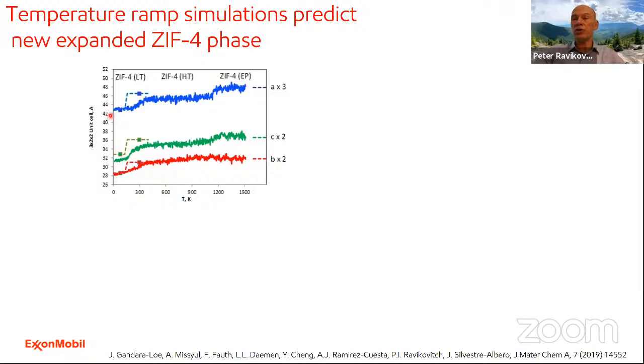When we did these simulations using the snapshot method with the temperature ramp on ZIF-4, we started with the low temperature structure. Then there is a transition to the so-called high temperature structure, and this is in agreement with experiments. Experiments are the dashed lines. But then upon further heating of the material to unphysically high temperatures, which we can do in computer simulations, we observed further expansion, and we called it the expanded phase.